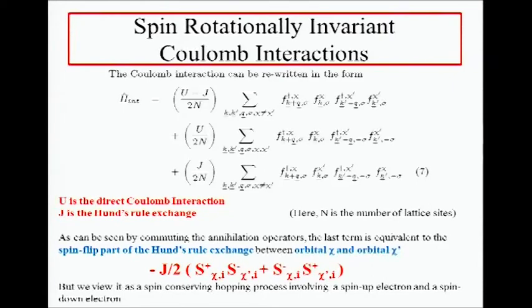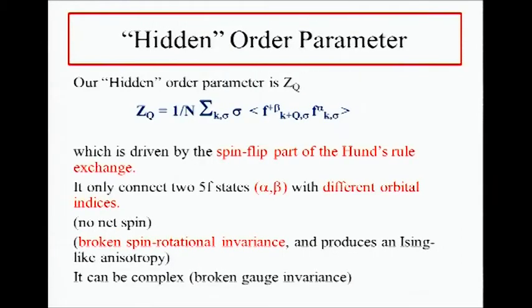However, the suggestion is that if you take this spin rotationally symmetric model and look at the Hund's rule coupling, specifically the spin flip contribution, you can have a breaking of the Hund's rule rotational symmetry and get a new order parameter which mixes states of different orbital characters.